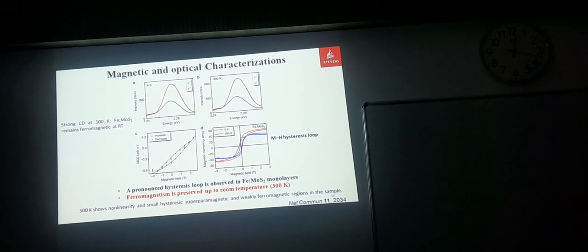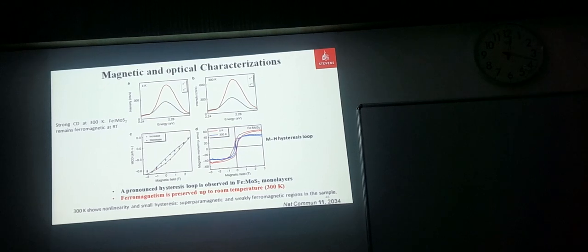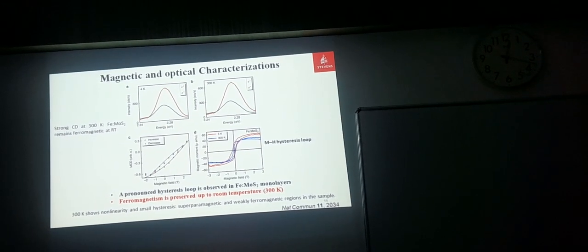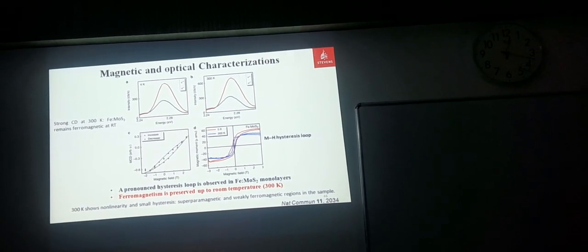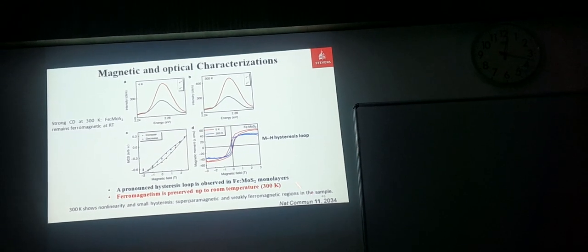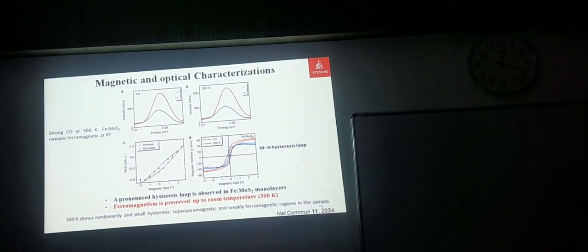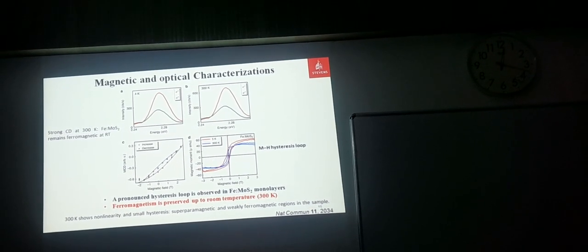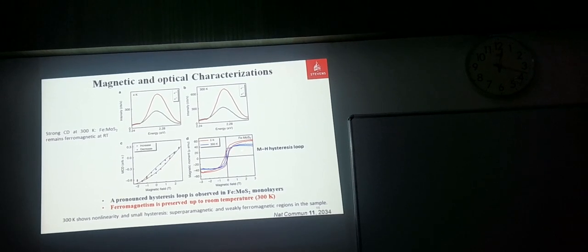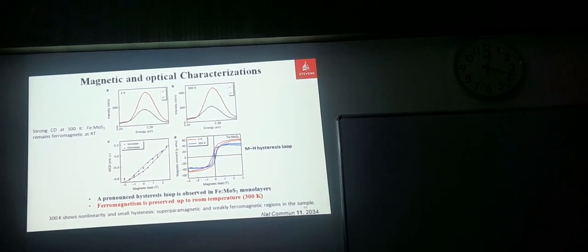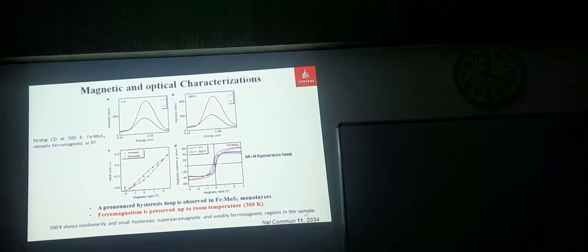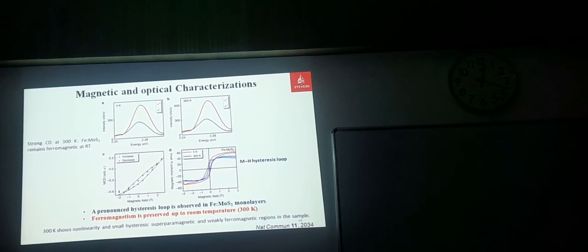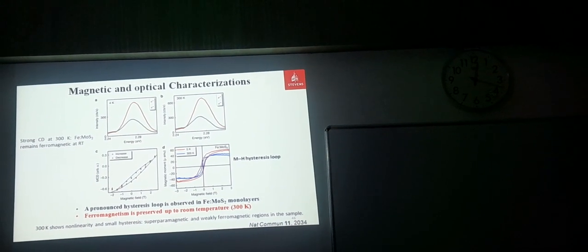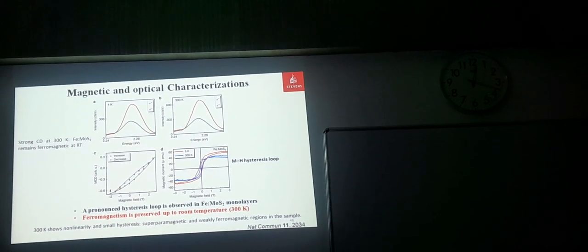I must talk about this one, because as I said, room temperature is most important to utilize this material for quantum technology or quantum devices or any device application. Here you can see the hysteresis loop. That is one of the important characteristics to confirm this material. Here you can see these two windows. The blue one is at 300 Kelvin, and the red one is at 5 Kelvin. We see the hysteresis loop at room temperature as well. That is one of the huge breakthroughs in the field for real next generation electronic applications, especially in quantum design.